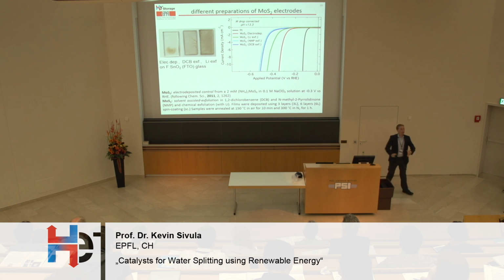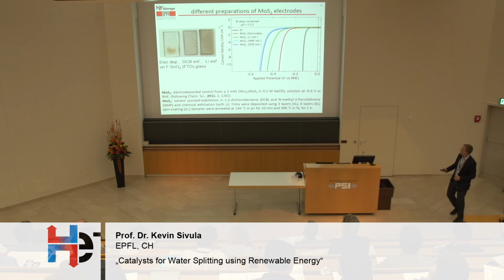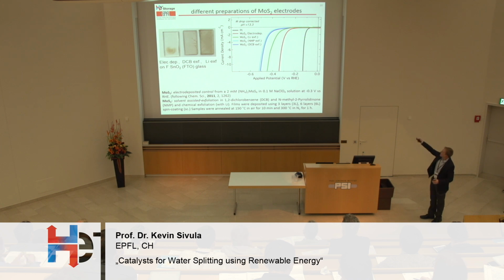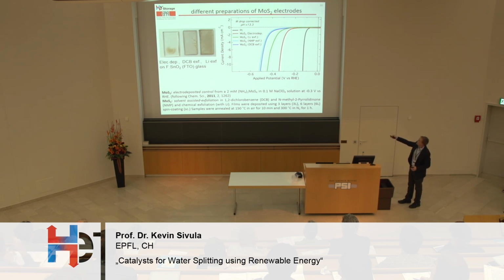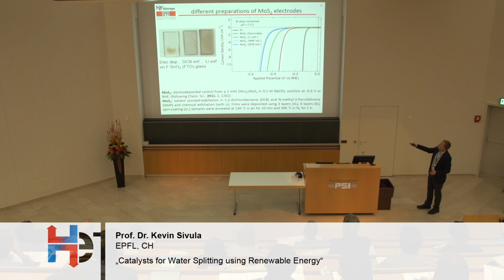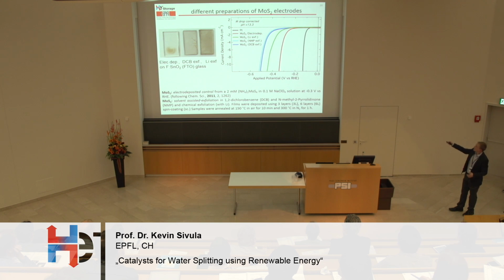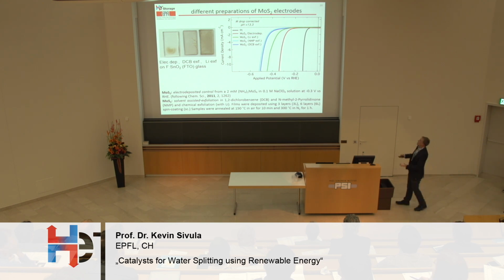And in fact, they work to reduce water pretty well. Now, here are these IR-corrected JV curves that I mentioned before. And of course, here is the platinum standard. So this is what we'd like to get to eventually. Here's the electrodeposited molybdenum sulfide following a known route. And our samples, which were prepared by a simple solution-based exfoliation, either using a lithium intercalation or two different solvents here, NMP or dichlorobenzene, performed reasonably well compared to the standard molybdenum electrode deposition, but not as good as it. And in all cases, they're still far away from the platinum.